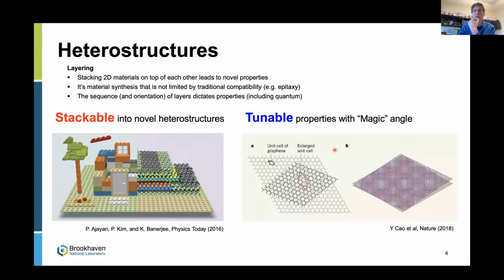And so people have shown these amazing things where just by changing the angle between the two layers, you can tune through all these different electronic states. And so in principle, you could imagine having two layers you put on top of each other, and by twisting it, you tune it between being an insulator and a conductor, or ferroelectric for some angle and a superconductor at other angles. And people have discovered for certain layers, graphene on top of graphene, there are certain magic angles that give really unique, interesting electronic and quantum properties.